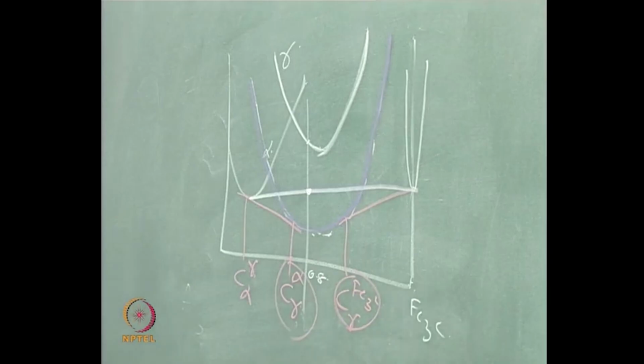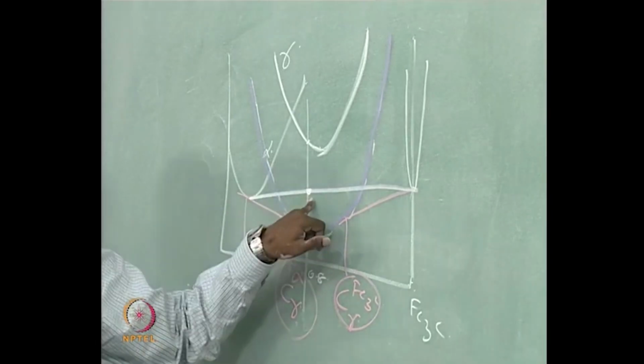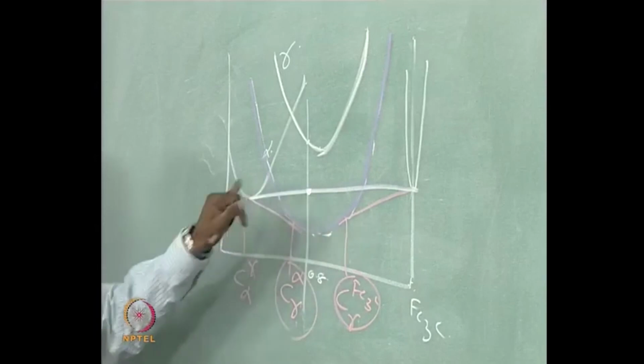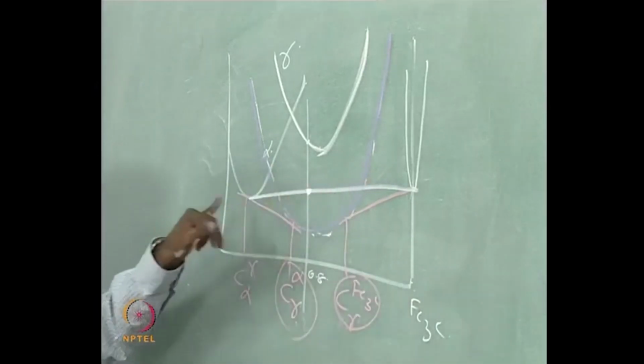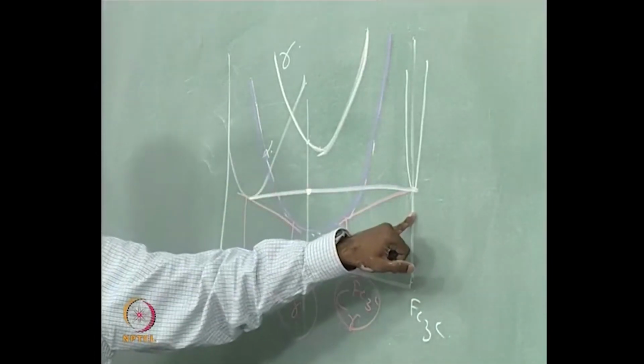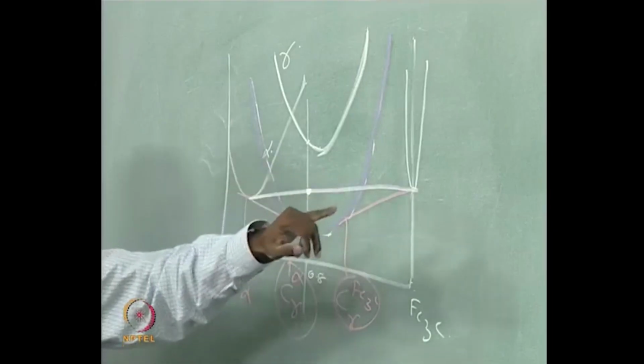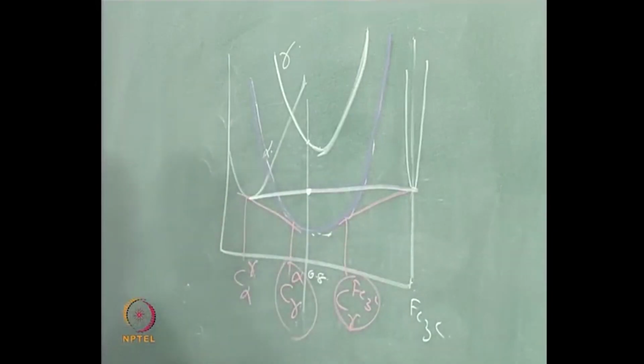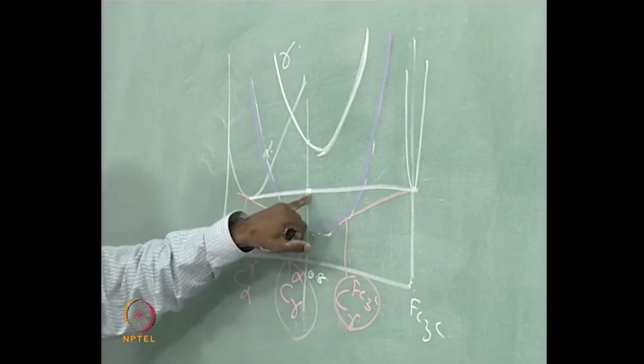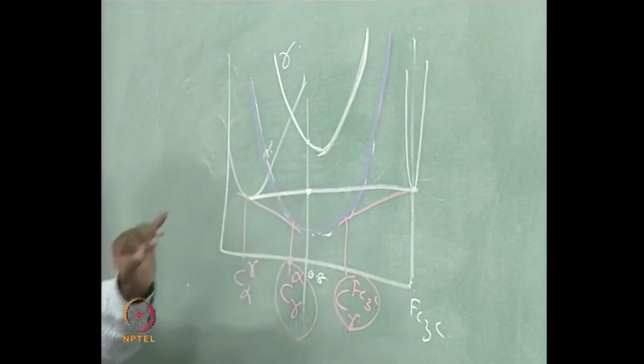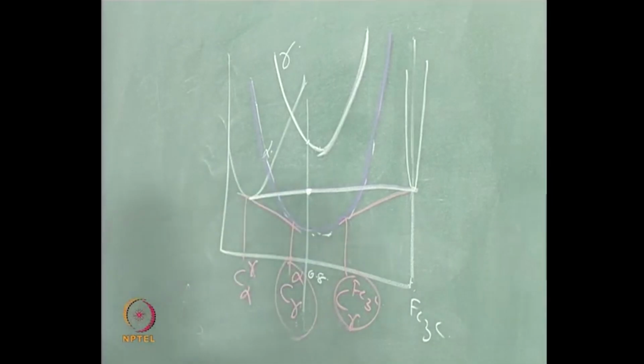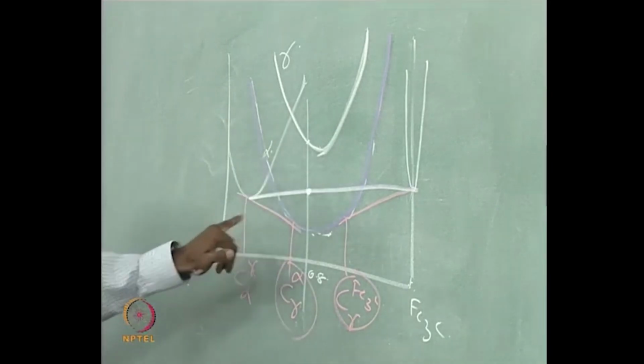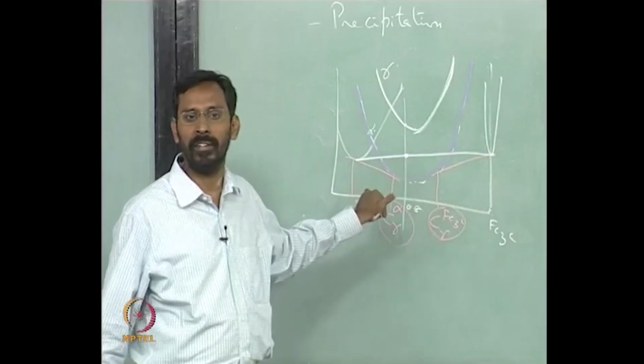The free energy of the two phase mixture is always a point on the line joining the two free energies. Whenever I identify any two phases, find out the free energies of it, draw a line joining the two free energies, and any point on that would give you a free energy of a mixture having an overall composition of this. The overall composition is this, but the individual phase compositions are different.